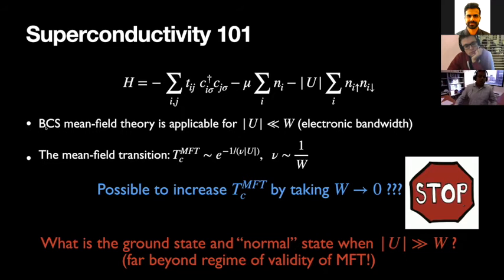By that I mean, when we apply BCS mean field theory, we typically start out with a metallic state that has long-lived and well-defined quasi-particles, and then we introduce attraction between these quasi-particles and study the Cooper instability. In this extremely non-perturbative regime where I have literally just one scale in the problem, the strength of attraction, it's far from being clear what the normal state will be like. So one needs to critically examine this problem.